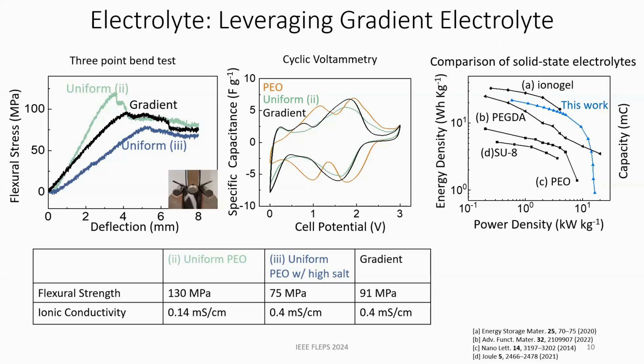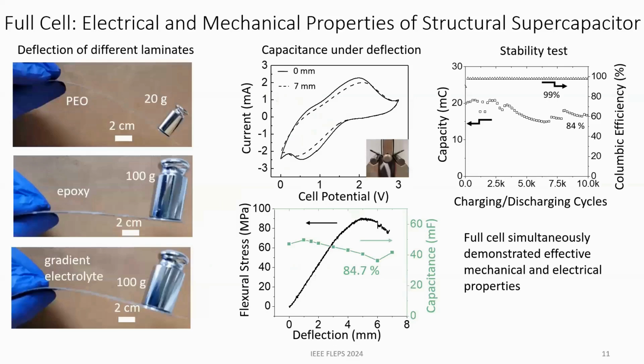So we won't achieve this performance because we have a need for mechanical strength. But you can see that our uniform PEO epoxy solid-state electrolyte, the green line, has slower kinetics, which is shown by the loss of the redox peaks, but our gradient electrolyte is able to bring it back. And if we compare our electrolyte to other solid-state electrolytes used in monofunctional supercapacitors, it can outperform these as well. So if it's good enough for those, it's good enough for our structural device.